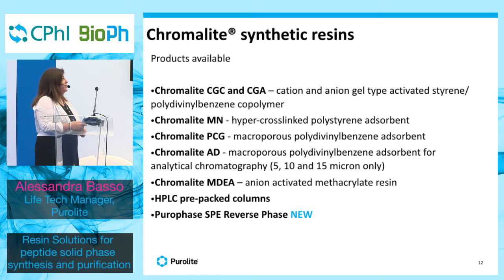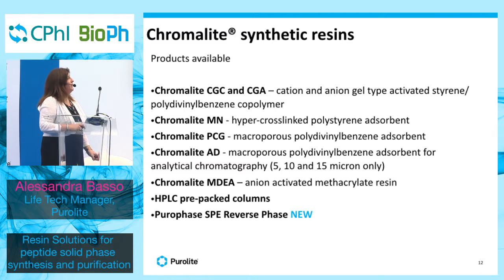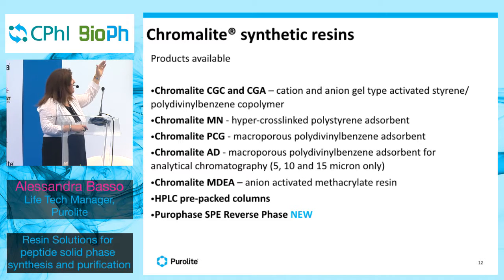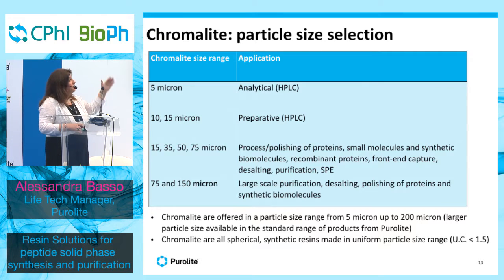So for peptide purification, among all the products that we have in Chromalite for molecule purification, the most interesting products are in the range of 5, 10, and 15 microns, so the AD product and the PCG product. They are strong, macroporous resins, because the peptide is a big molecule, polydivinylbenzene, so very chemically stable, and adsorbents that can also be functionalized to get ion exchange functionalities. Here, to show you the particle sizes that we have available using proprietary technology, I will show you at the end a nice picture of how we make these resins.